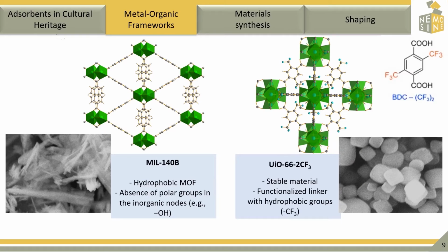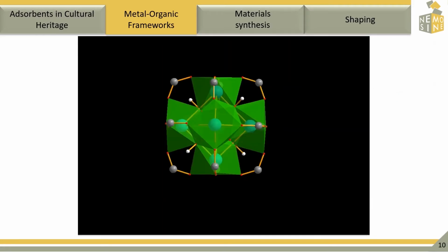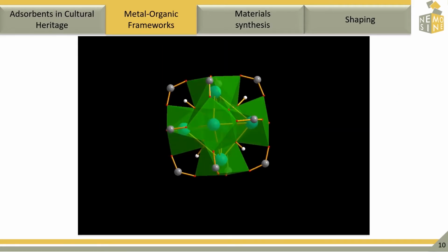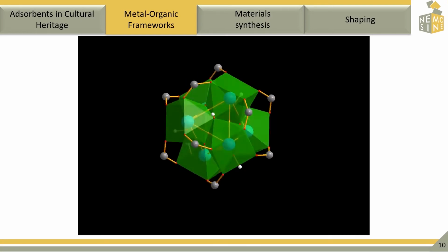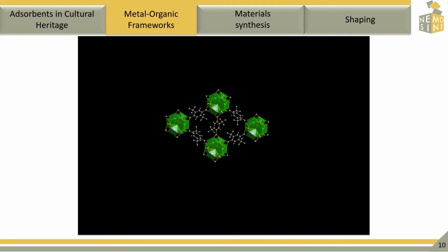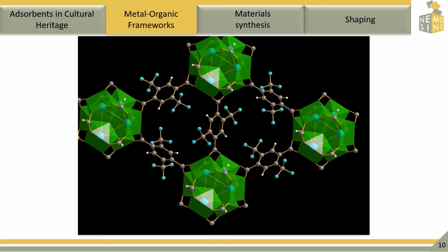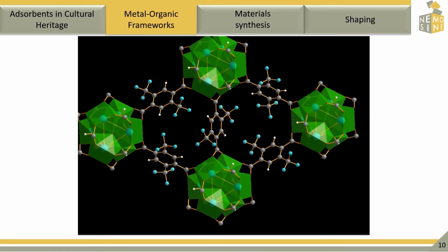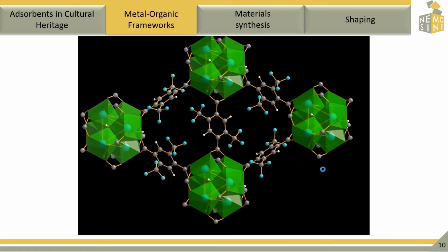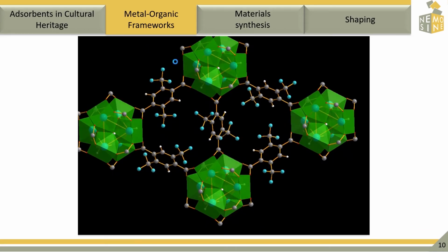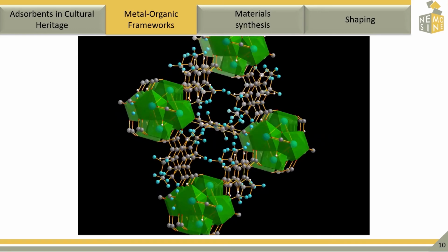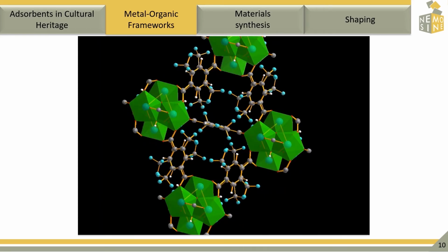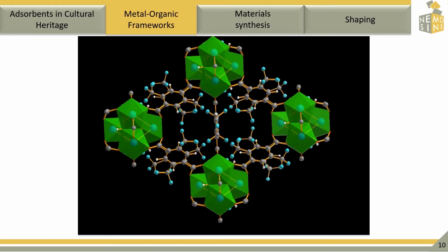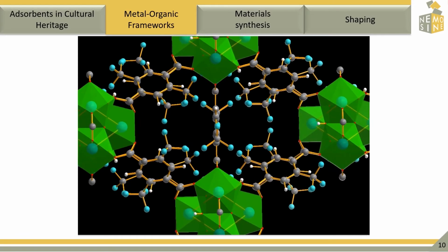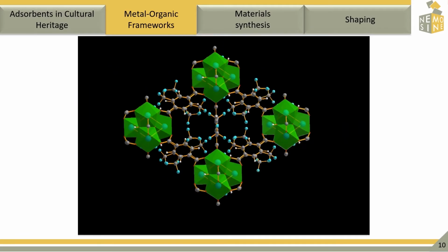One other performant MOF is UiO-66-2CF3. This MOF is similar to the UiO-66, which is a MOF that is based on zirconium octahedral clusters that form a lattice in an ideal 12-fold coordination with dicarboxylic linkers, resulting in a cubic packed unit cell structure. The high zirconium charge and elevated connectivity of the nodes accounts for an exceptional chemical stability and thermal and mechanical resistance. In addition, since it has bulky CF3 groups in the linker, it increases the hydrophobicity compared to the non-functionalized structure, decreasing the affinity towards water.